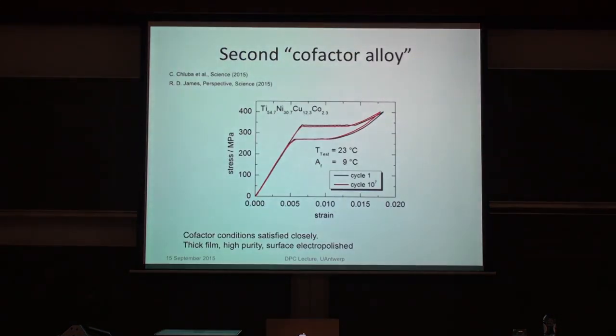Okay, but now, as I say, there's been a recent development in this area which I consider spectacular. This is a material undergoing a big first order phase transformation. It's undergoing the full transformation, although the strain is not so big, but anyway, it's a full transformation. And this black graph is the first cycle, and this red graph is cycle 10 million. And this is very unusual in phase transformation. So that's nearly perfect reversibility after 10 million cycles.